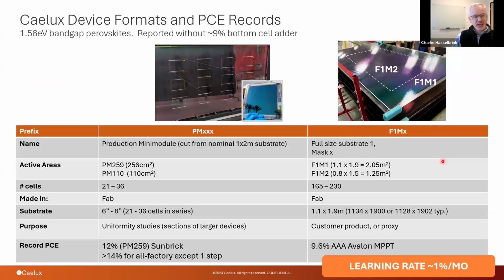All right, so here's some of our data. We've got 1.56 eV band gap perovskites, so these are not tailored to capturing records. The main thing that we're trying to do is make a great tandem, not necessarily the perovskite itself. And when we build these in the factory, we build them in multiple formats. We've noticed a lot of people report results in different formats. They might report a hero cell that's less than a square centimeter. We try not to do that. We try to be really crystal clear about what we're talking about. And the other part is, was that made in the lab or was that made in the fab? And is that the same chemistry as you're getting for the durability numbers that you're reporting?